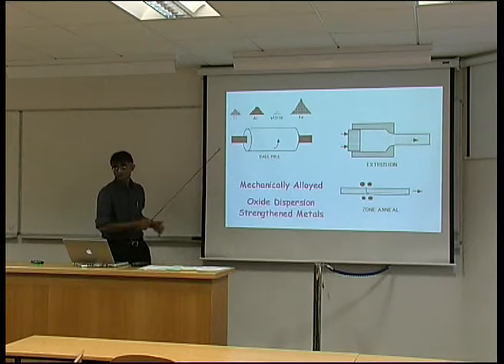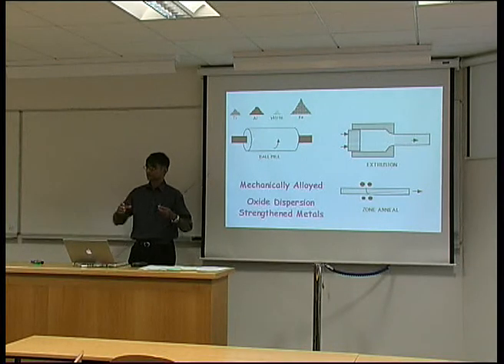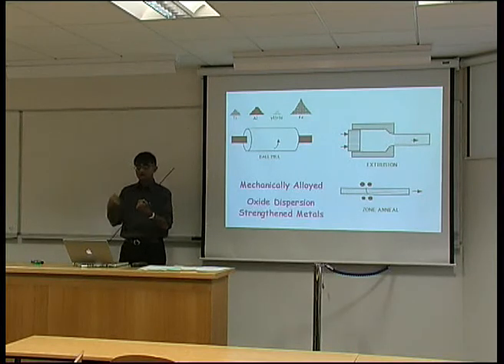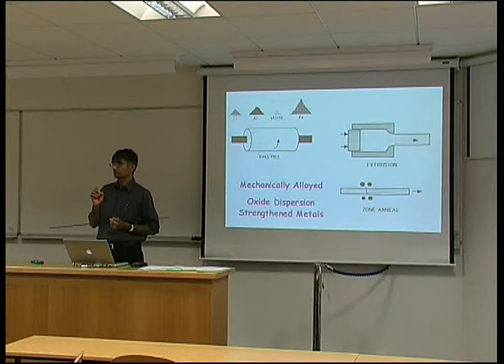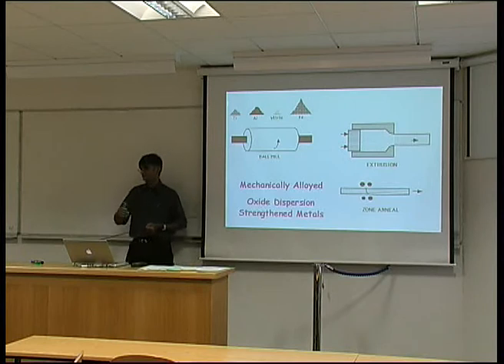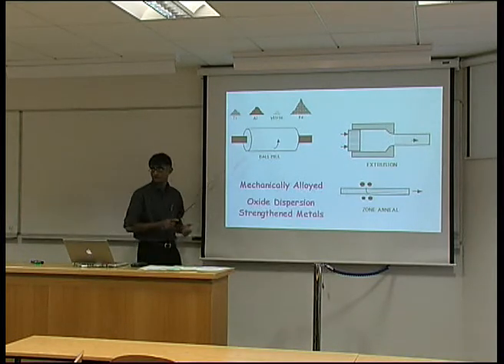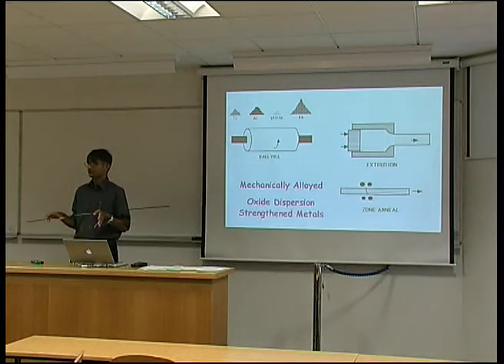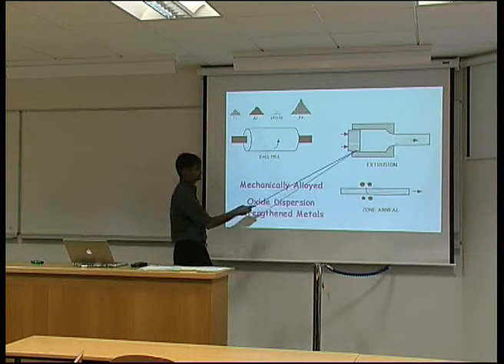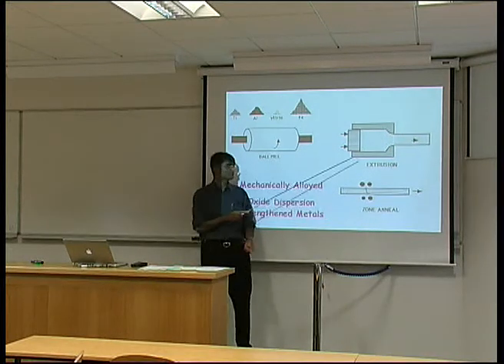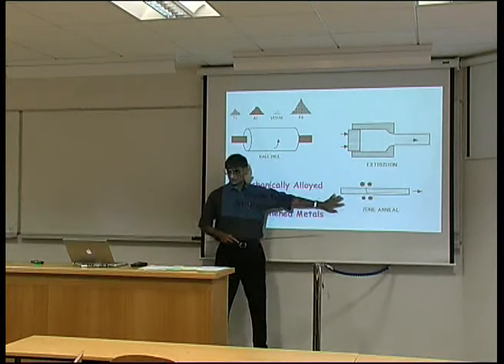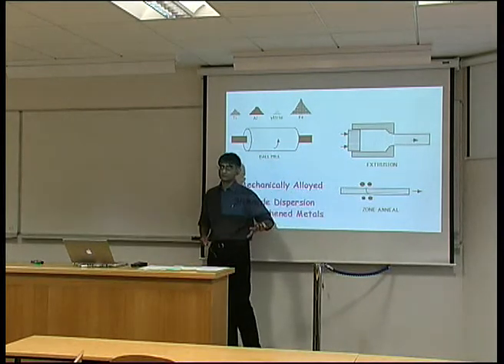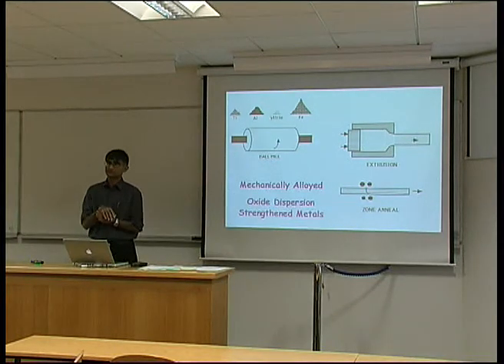We take these powders and put them into a cylinder which contains cast iron balls. When the cylinder rotates, the balls impact against the powder, weld the powders together, break them up, weld them up — so many times that eventually you end up with an atomic solid solution. This is still a powder, called a mechanically-alloyed powder. You then need to consolidate it — make it into a solid lump. So you extrude it, just like plasticine. You're taking metal and applying huge forces, joining up all the particles in the solid state, and then giving it some heat treatment to get exactly the right properties.